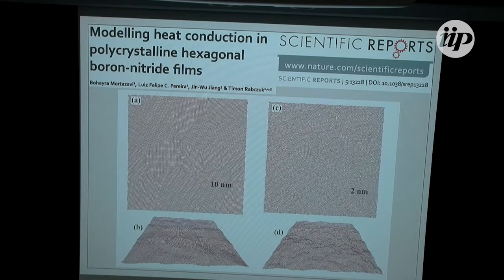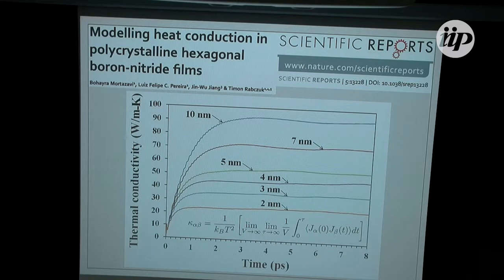Just to finish, we also looked at other things that are not made of carbon. For example, boron nitride. That's polycrystalline boron nitride. This is what happens when you grow these 2D materials by chemical vapor deposition. Here the average grain size is 10 nanometers. Here it's about 2 nanometers, harder to see the grain size. We calculate the thermal conductivity with equilibrium MD as a function of the grain size, and we see that as we increase the grain size, the thermal conductivity increases.